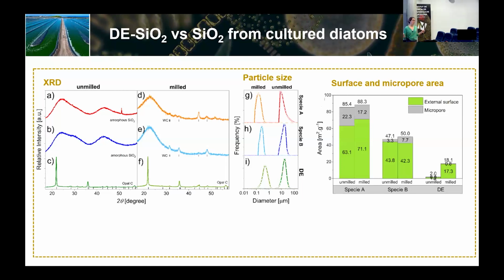So we did the same thing we did with the diatomaceous earth, and actually we compared the results with it. So in this case, we have an amorphous silica. We did the ball milling with tungsten carbide, the same as we did with the diatomaceous earth. We checked differences in particle size and changes in surface area. But now what we see is that this surface gain that we had from the diatomaceous earth, now we don't see a clear gain when we do the milling of the material. Of course, we kind of have to do this just to help the pack density of the battery. But it's not that you will gain much in terms of surface, and this is due to the morphology of these particles. They are so thin that just cutting it into pieces doesn't give much surface gain.